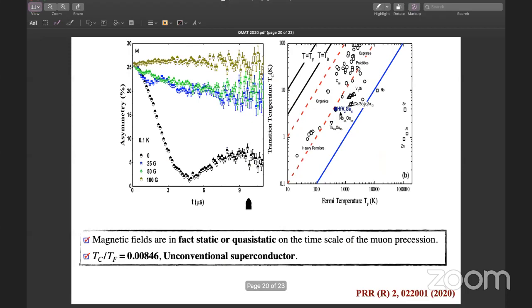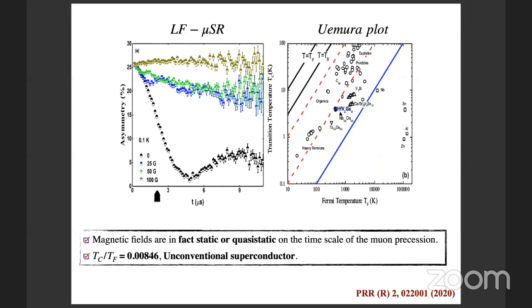Okay, so we have also measured the longitudinal μSR to check whether any impurity is present in our system, or what the values of the internal magnetic field in this system are. So we find that if we apply a very small magnetic field, like 100 Gauss, then we have a full recovery of the polarization, the asymmetry.